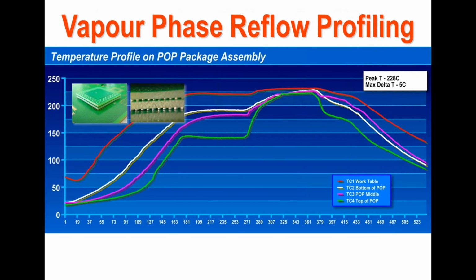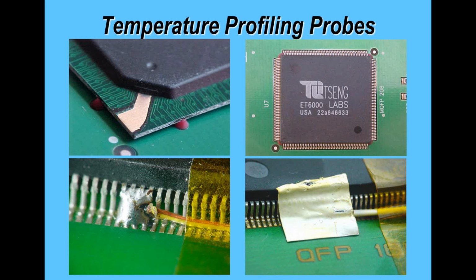If we compare that with the vapor phase profile, here we've got a step profile with preheat, and we've got 228 degrees Celsius and a 5-degree differential. So a much smaller differential for the process with the same product. So again, where you monitor obviously has an impact, and what you're actually running obviously has an impact with the process that you're going to be using for production.